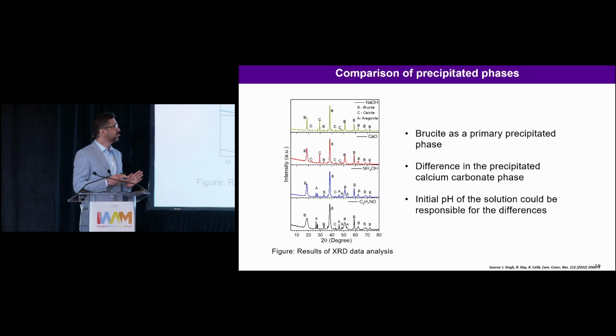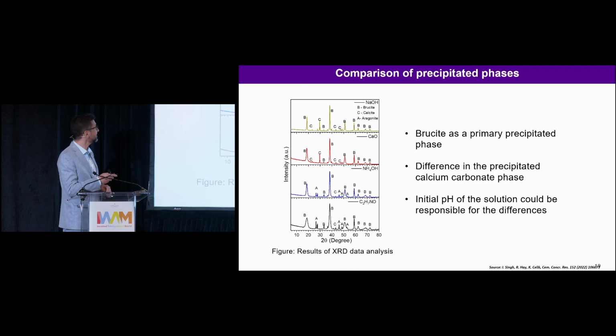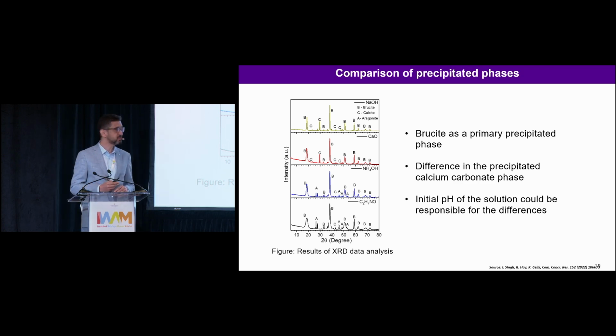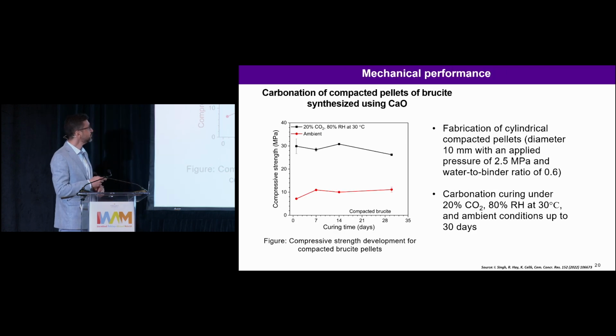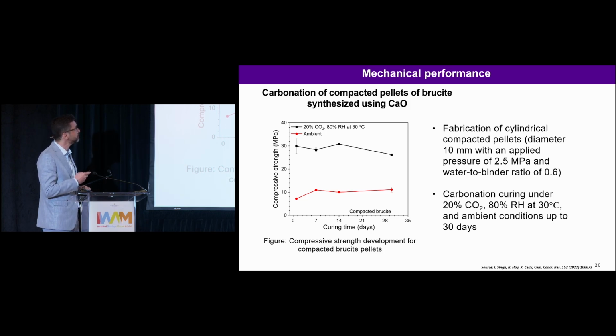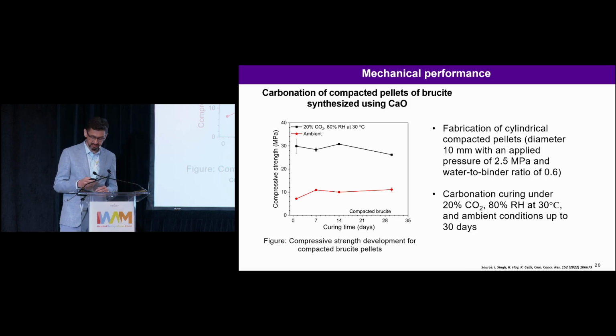The primary phase in the precipitate with different alkalines, as mentioned, is brucite, and there are some trace amounts of calcite or aragonite. Most likely it is because of the initial pH of the solution used. And once we have this brucite, we need to cure it in an accelerated carbonation condition to increase the strength gain. The one cured in air reached around 10 megapascal, but once we accelerated the carbonation process with 20% CO2 and 80% relative humidity at 30 degrees Celsius, the strength development is significant, around fourfold with respect to ambient curing condition. And 30 megapascal is sufficient for most structural or construction applications.